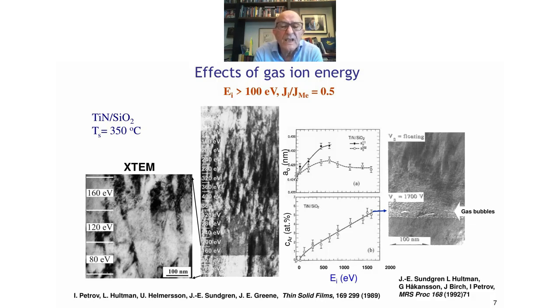If you look at the graphs, we build in stress in the films, and out-of-plane lattice constants become higher. And in the bottom graph, we trap a lot of argon, several percent. And if you go to 1700 volts on the right picture, you see a lot of gas bubbles. So bias sputtering is useful if we maintain the energy as low as possible, in the range of 100 eV, depending on the plasma density, at the expense of residual stresses on the order of several gigapascal.